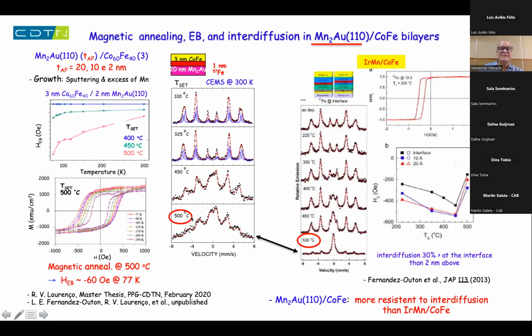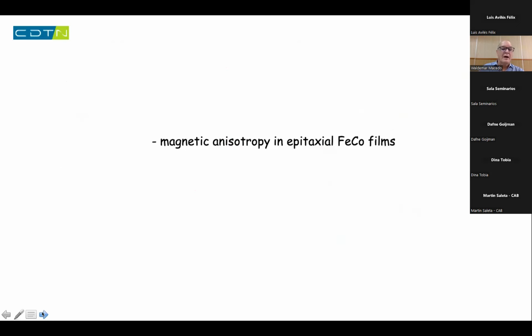You see that at 500 centigrade, we still have, let's say, a strong ferromagnetic spectrum, much more robust than iridium manganese. Let me change now to an epitaxial system.